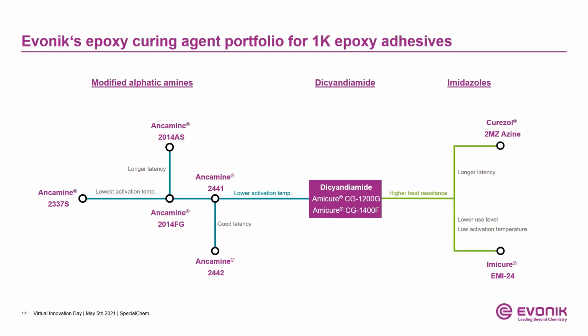Starting in this case from dicyandiamide, the next right choice for a lower activation temperature, for example, will be the Ancamine 2441. When you're looking for low activation temperatures, they can be achieved with Ancamine 2014FG and Ancamine 2337, just following the tube map to the left side. Beside these, we also offer Ancamine 2442 and Ancamine 2014 AS in case improved shelf life is required.